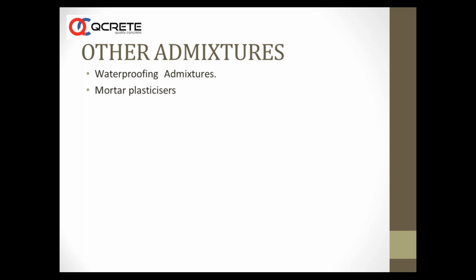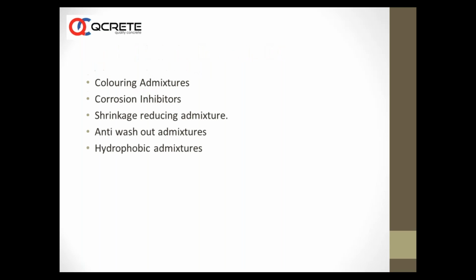Then mortar plasticizer also has some amount of air in it actually. The mortar plasticizer should give properties as we discussed already. One is water retentivity and then water reduction and then some amount of air. These three are important. And also a mortar plasticizer should give some amount of retardation, some amount to increase the shelf life of the mortar or plaster. Other admixtures, you have coloring admixtures, various kinds of iron oxides and things like that are used to give different colors.